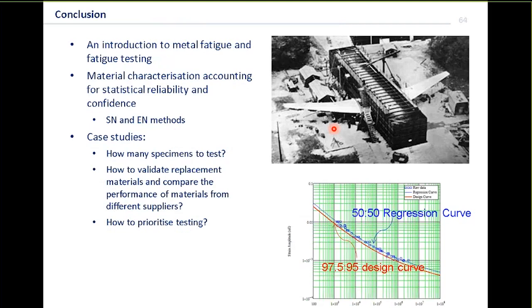And basically we've said if all we want is a regression line, 15 specimens is probably your minimum. But if you want a design curve, then you should be looking at about 25 specimens at least. Otherwise, you'll end up with big safety margins coming in or problems with bias in how that curve's distributed. We've also looked at an example where we've validated replacement materials or plug-in replacements for different materials from different suppliers, even if they don't necessarily know what the original loading was. Now we've looked at examples of how we can use simple statistics to help us prioritize testing.